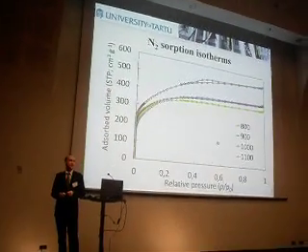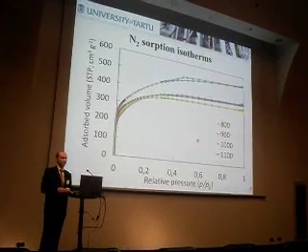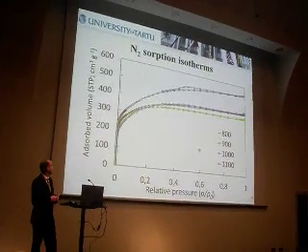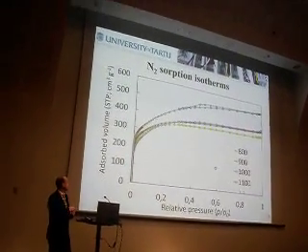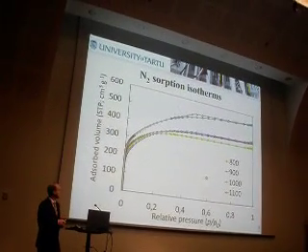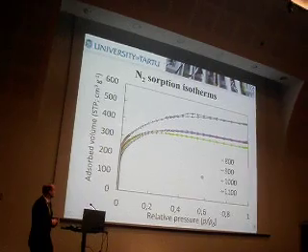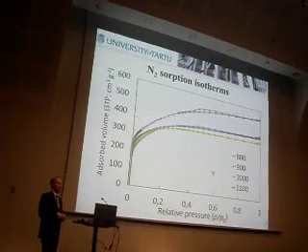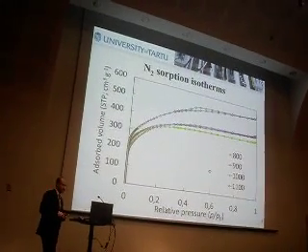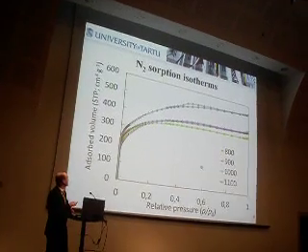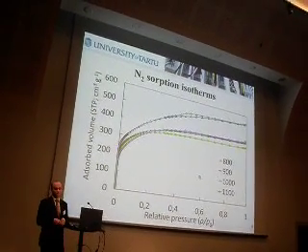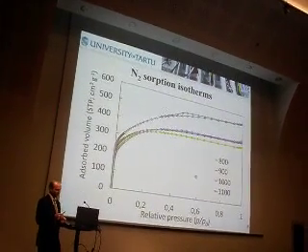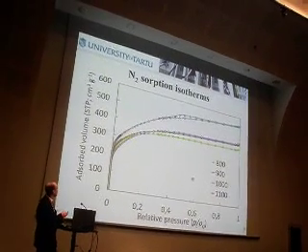And also we performed low temperature nitrogen sorption, and from that data we can see that isotherms are all type 1, which means that the material is almost all microporous. And we can see that slightly higher specific area is for